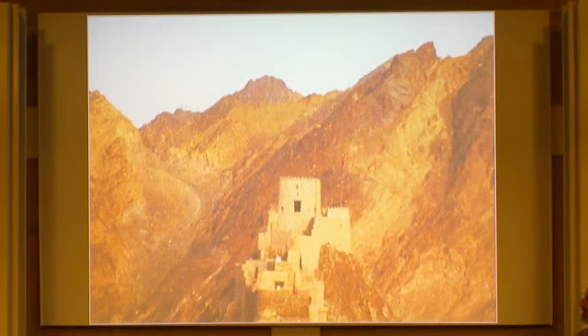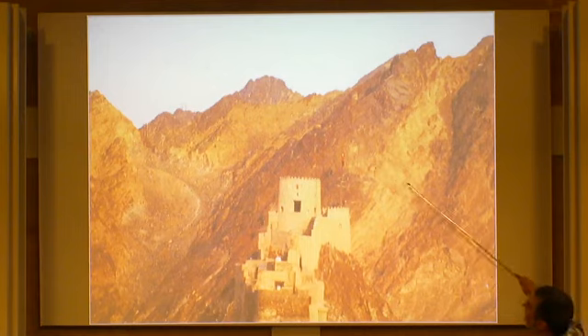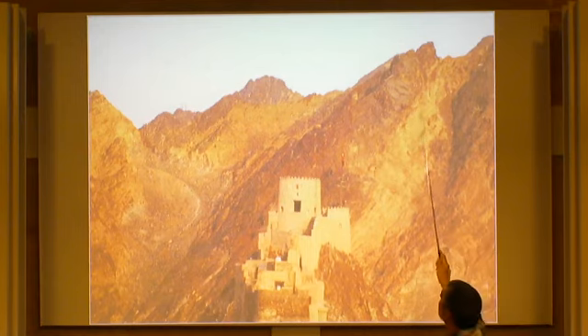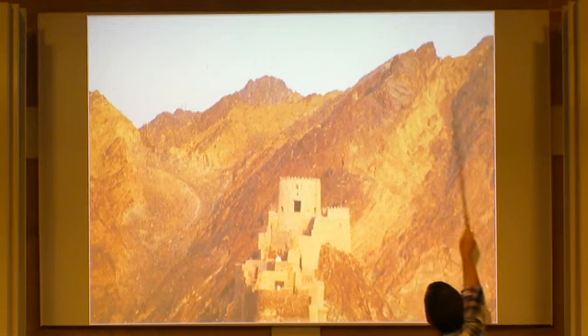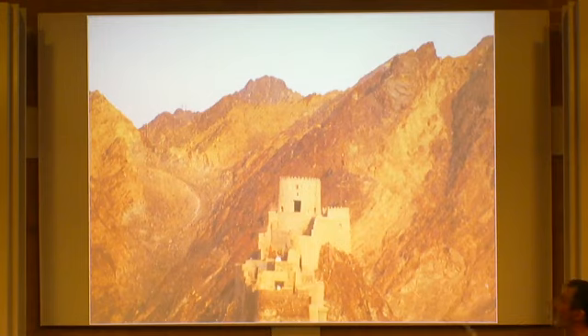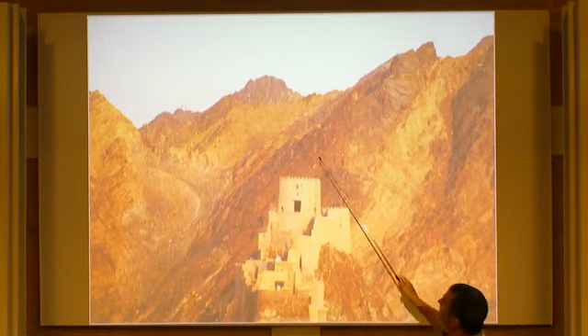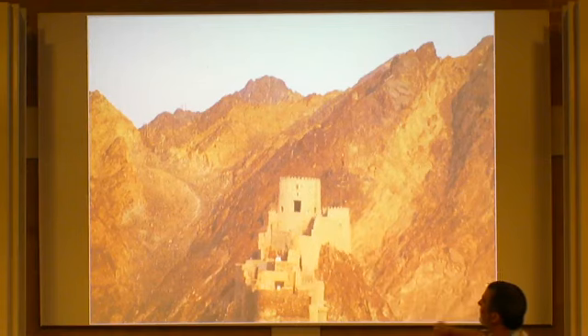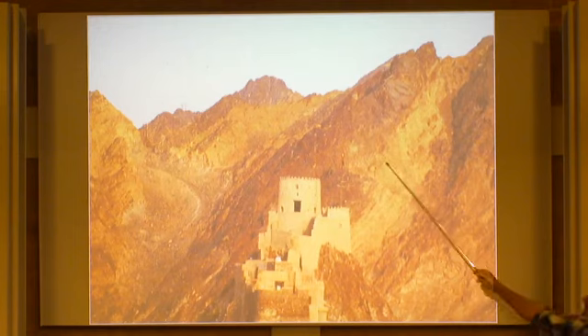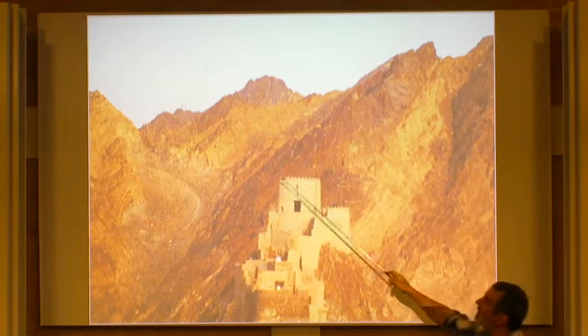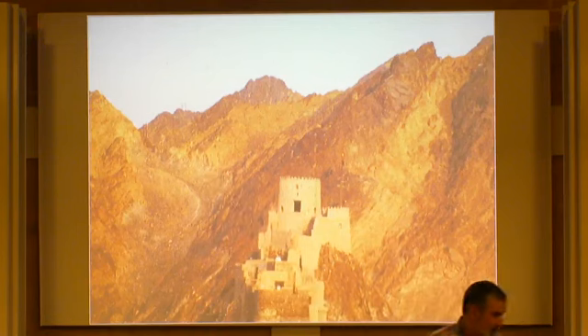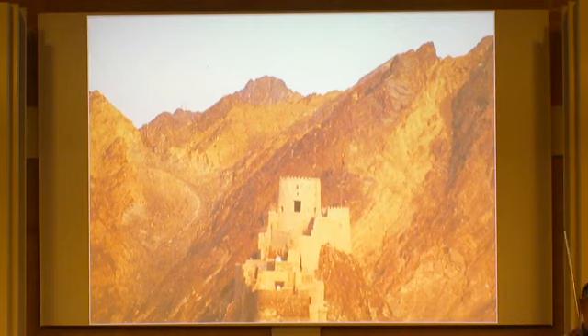Some of them get quite big. These dun-colored rocks here are big wide dunites, olivine with a little bit of chrome spinel, and the brown rocks around them are residual mantle peridotites. They don't have a lot of clinopyroxene in them, so we call them Harzburgites. And here's a castle for scale. You can see that the big dunites are on the order of 20, 30 meters thick, and in fact the thickest one we know of, not too far away from this castle, is about 100 meters thick.